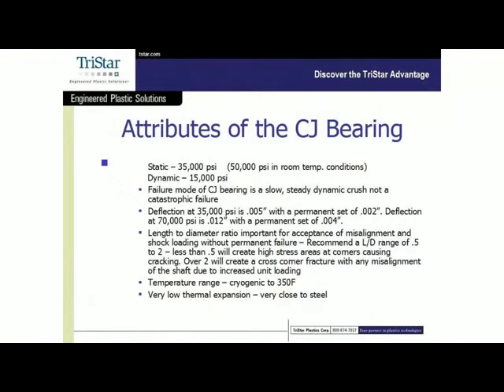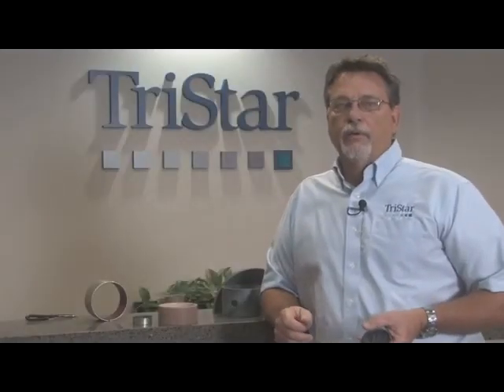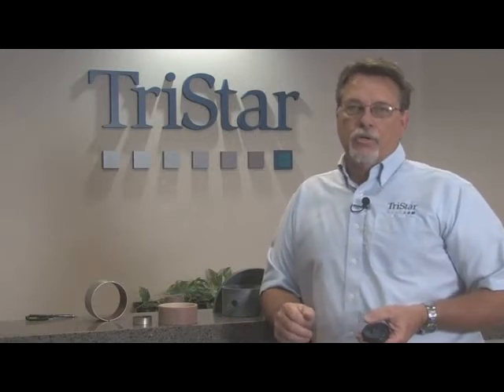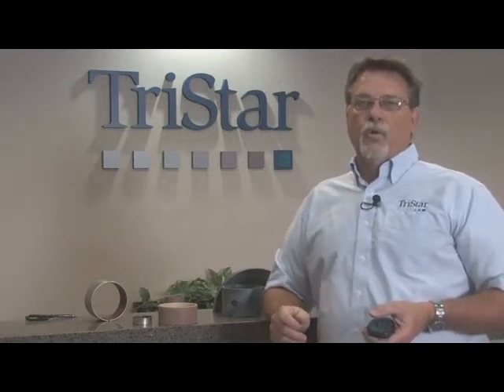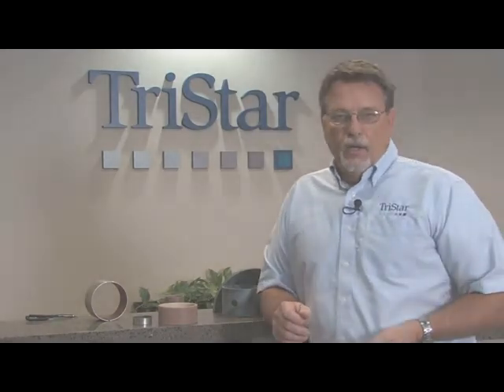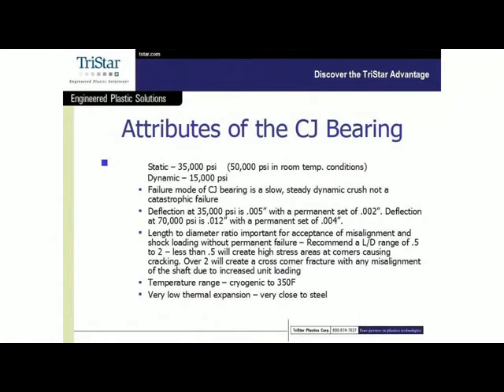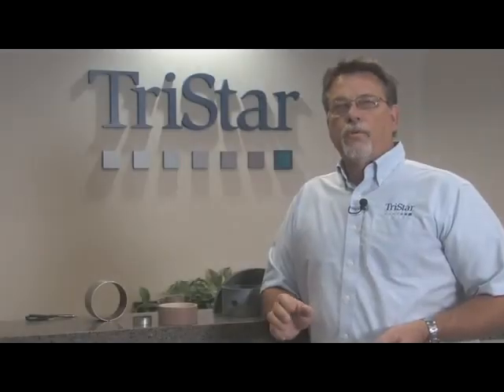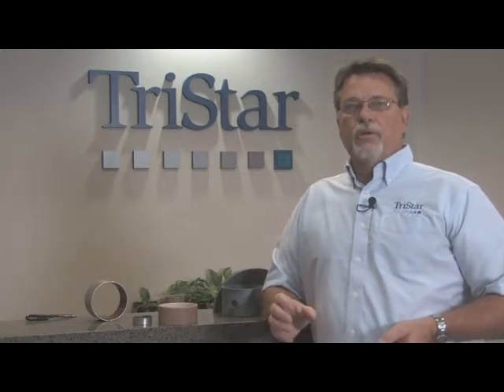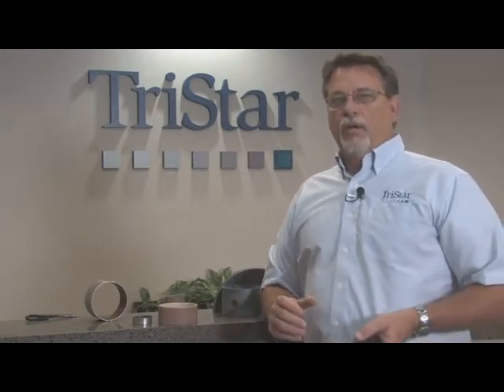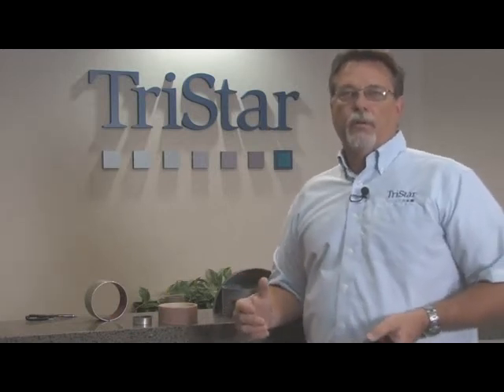The temperature range of the CJ is very similar to the UltraComp. It's cryogenic up to 350. And when we talk about cryogenic, we're talking about being able to go down to cryogenic conditions without embrittling, without cracking beyond recognition. So it's a very good material, as is the UltraComp, for very low temperatures. The thermal expansion of the CJ is very close to steel. So what that allows us to do is to run tighter tolerances. We can control the expansion and contraction conditions if you've got a broad temperature range, and much more so with the CJ than UltraComp.